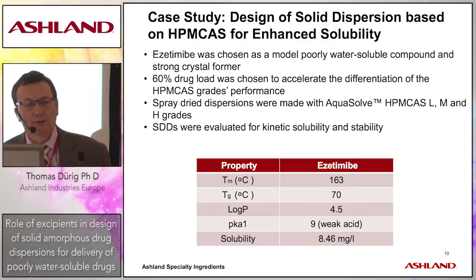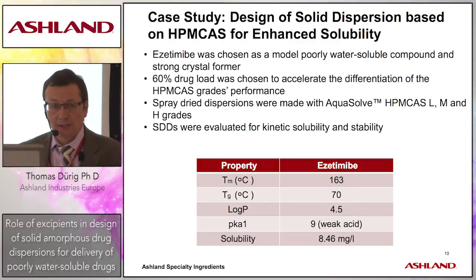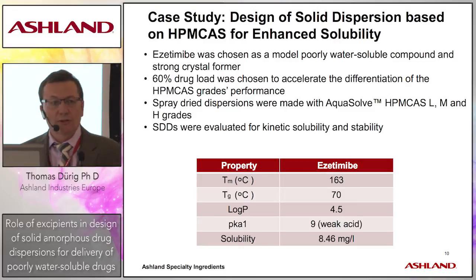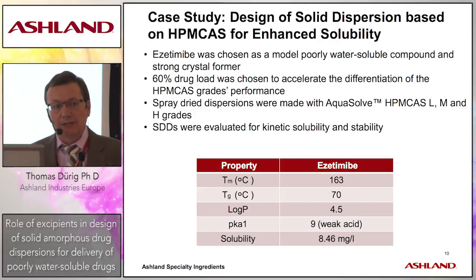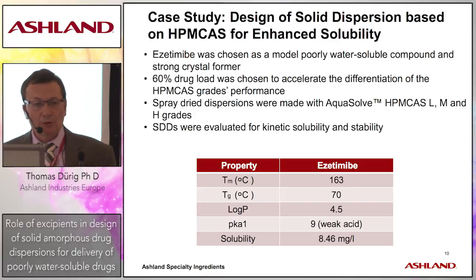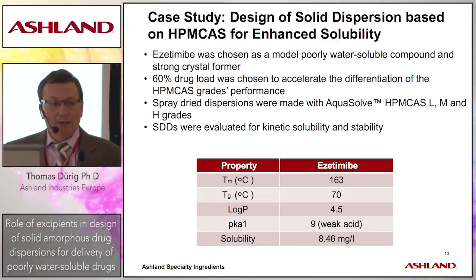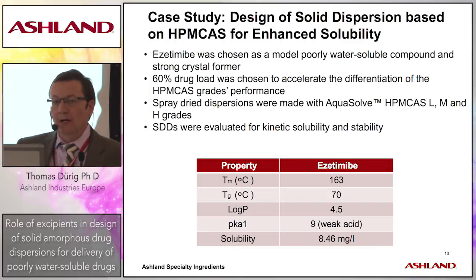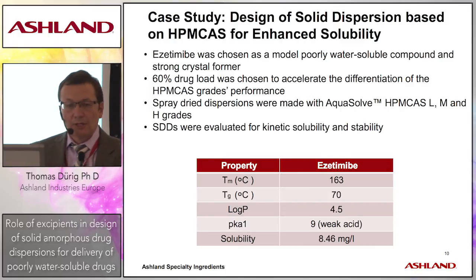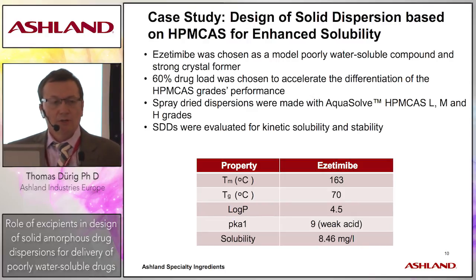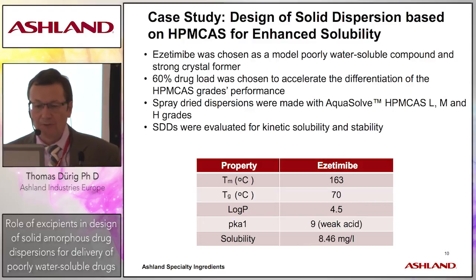So this is a drug where you have both challenges in maintaining the amorphous state in the dosage form, so the solid tablet dosage form, and preventing it from recrystallizing before it is given to the patient, as well as then once it's actually dissolved in the gastrointestinal tract, and you have that, if you remember the spring effect, when you have that high saturated solution, Ezetimibe tends to recrystallize or precipitate very rapidly. So to extend that parachute tends to be a little bit of a challenge.